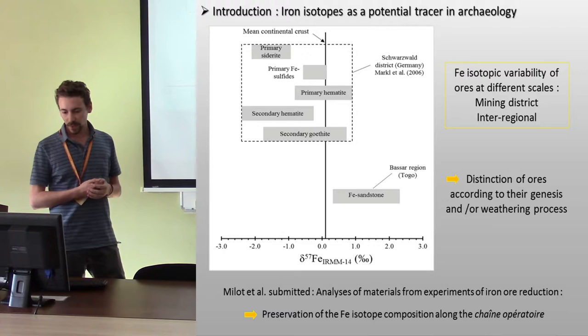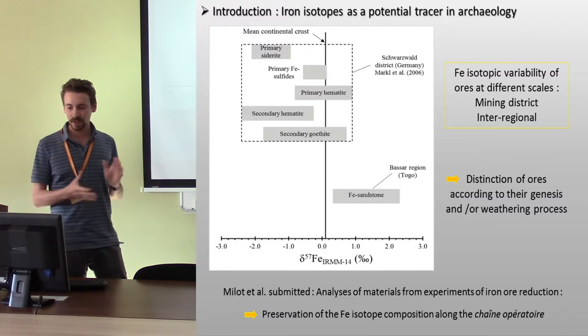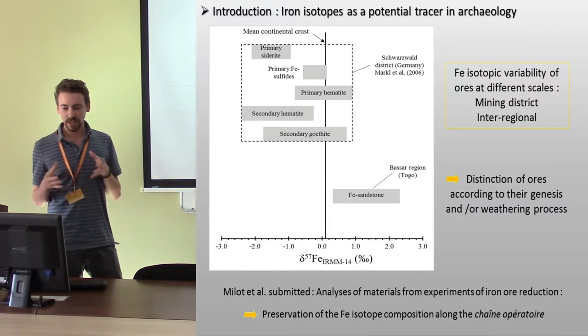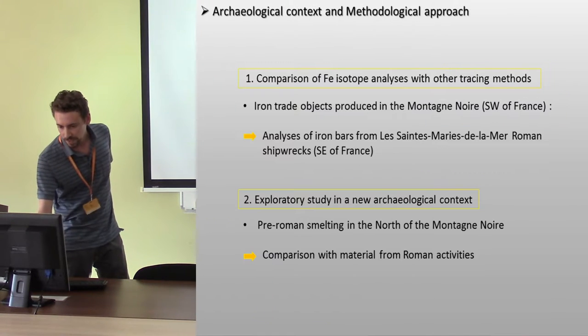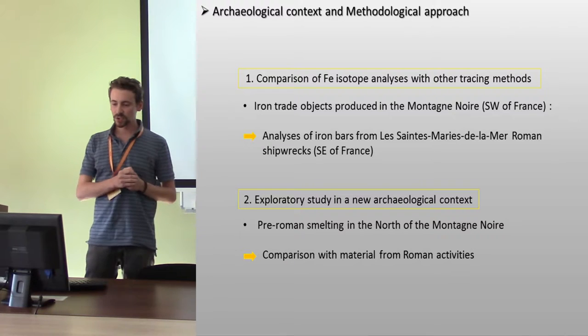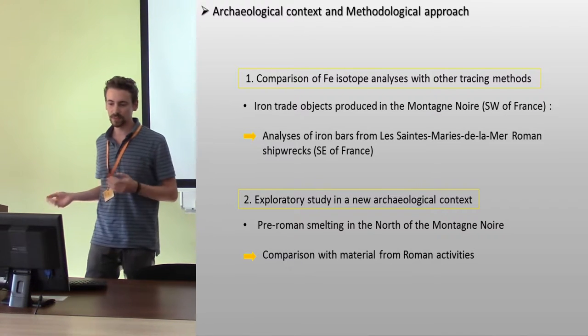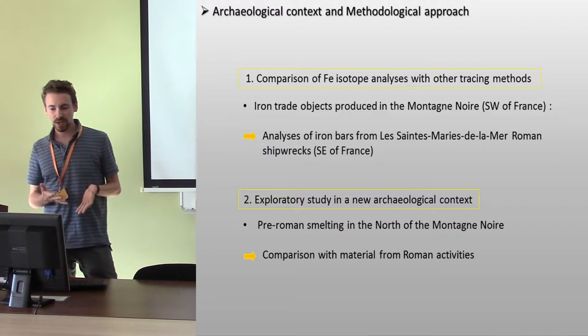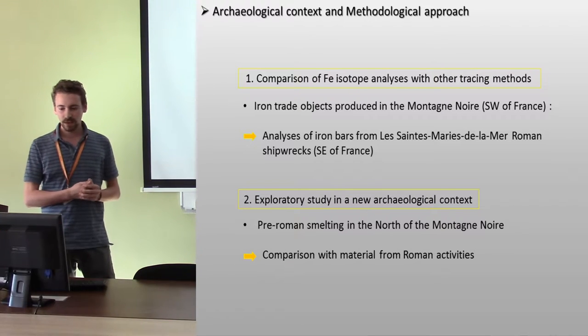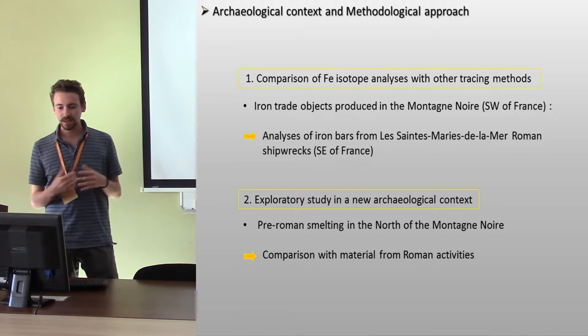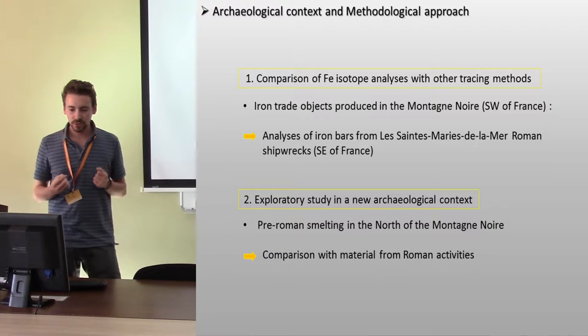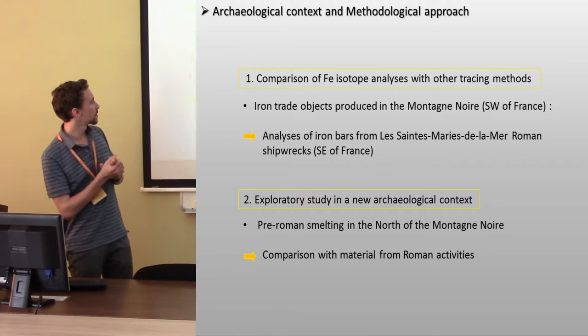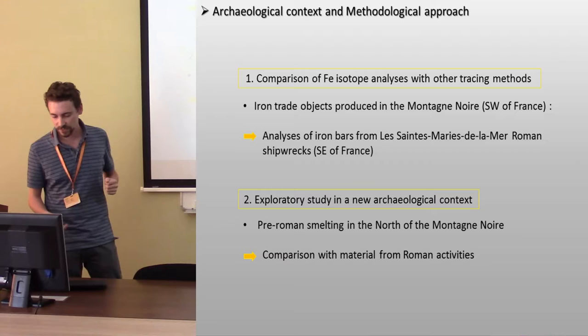During the first part of my PhD, we analyzed materials from experimental iron ore reduction, and we demonstrated that the iron isotopic composition is preserved all along the chaîne opératoire. In order to validate this new approach, we tried to compare our results with those of other tracing methods. We analyzed iron trade objects, and in particular iron bars which have been found in Roman shipwrecks near Les Saintes-Maries-de-la-Mer in the south-east of France.